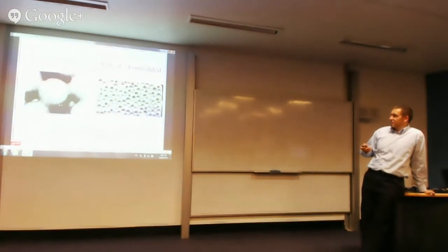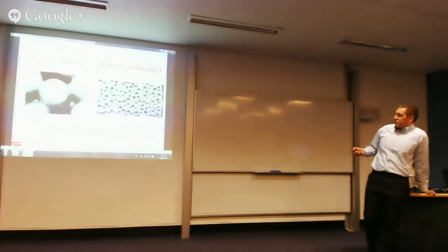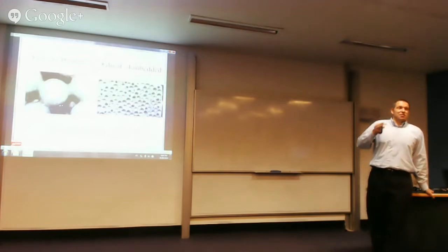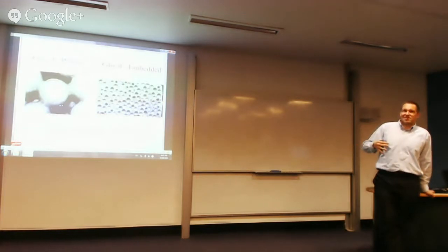Here on the left-hand side again, partially glued, so this is zoomed in. We have the spheres, and in certain points, the spheres are adhesively joined. And here on the right-hand side, it's a different idea, taken from classical composite materials, where we normally would have fibers embedded in the matrix, and the idea was here to embed the spheres in the matrix. The interesting thing is comparing properties between these two configurations, so just partially joined together or completely embedded. The weight doesn't change so much, but the macroscopic properties are completely different. And again, there is no better or worse, it's just a variety that we can offer for certain problems.